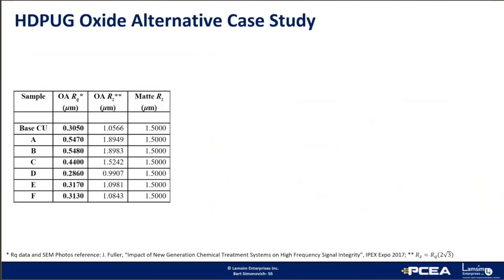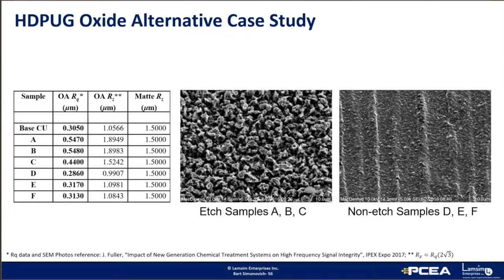In 2017, Jim Fuller from the HD Pug User Group published a paper at IPEX Expo. They basically studied six leading oxide alternative treatments. In the table shown here, roughness numbers are listed and compared to the base copper. A, B, and C were etched type, while D, E, and F samples were non-etched type. These two pictures are example roughness profiles for etching and non-etching on the drum side of the foil. The etched sample picture clearly shows the underlying profile has been altered significantly and looks quite rough compared to the non-etched samples, where you can see the underlying roughness profile of the drum surface is still there.